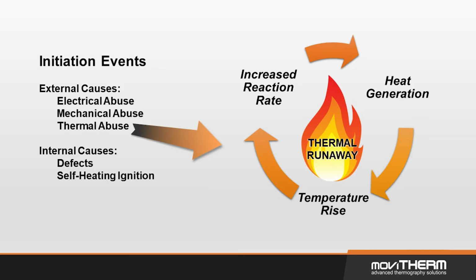Jerry, what are some of the things that you're seeing, and how can infrared impact this phase of the battery life cycle? Yeah, I think obviously, like Marcus mentioned a little bit about thermal runaway. So for people that don't know, thermal runaway is basically a situation where the battery or cell has something happen to it where it reaches a critical temperature, and that temperature actually triggers a chemical reaction inside the battery that generates even more heat, and then that increase in temperature further accelerates that reaction, creates a bit of a feedback loop of ever increasing temperatures, to the point where a fire or sometimes even an explosion, if there's a lot of pressure that builds up in the battery, can actually happen. So it's something that people are aware of.